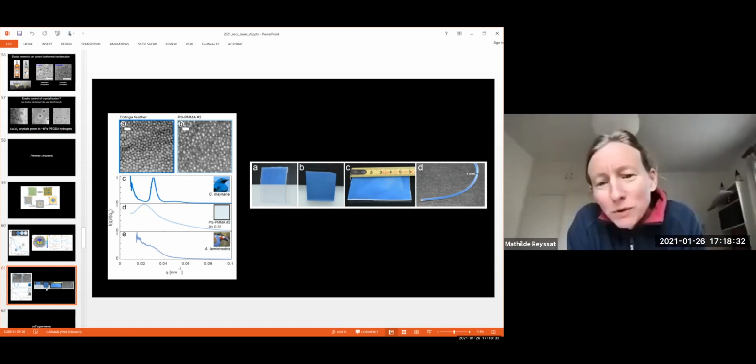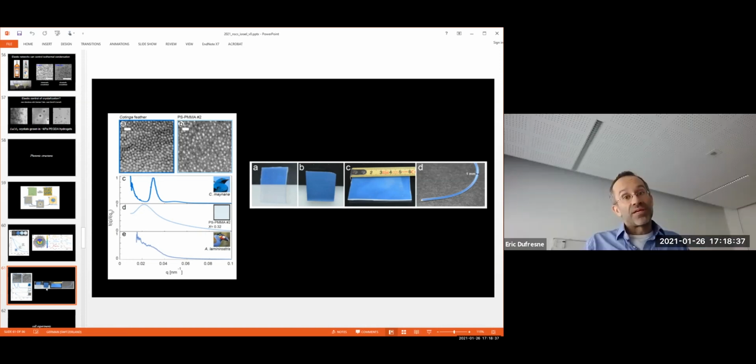And were you able to make very different colors? Not yet. The problem is that this beautiful blue color is the color of the sky, right? To get the color of the sky, all you need is really small objects that have a significant scattering cross section, smaller than the wavelength of light, but that scatter well and are uncorrelated. That's all you need for a blue color.